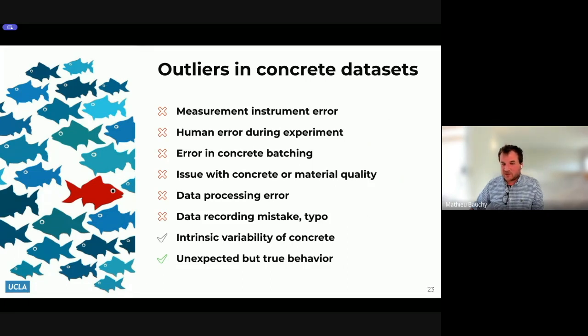So it's really a challenge when we work with concrete datasets to be able to clean the database, to remove those that are associated with actual errors, whether it's a typo, unit conversion, etc., but also to keep those data points that may not behave as expected, but are actually true behavior, because maybe those are the ones we care about the most. Like if we really want to find a new type of concrete that has a much lower carbon footprint, but still a high strength, maybe this is going to initially appear as an outlier. So we can't just remove everything that doesn't appear to behave as expected.